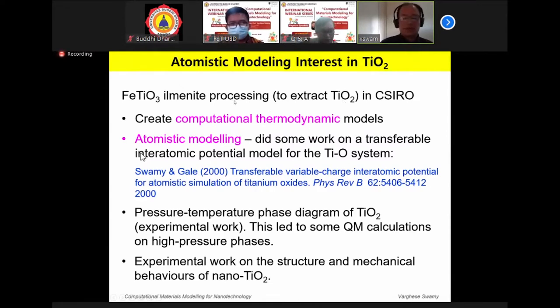That's the work I started off with, and I was planning to create a computational thermodynamic model for the ilmenite extraction. But when I looked into the data in the literature, I realized there isn't much available even for titanium dioxide or the Ti-O system. So that's where I got started with TiO2. So initially I did some computational thermodynamic calculations, and then I extended that to atomistic modeling of the titanium oxygen system.